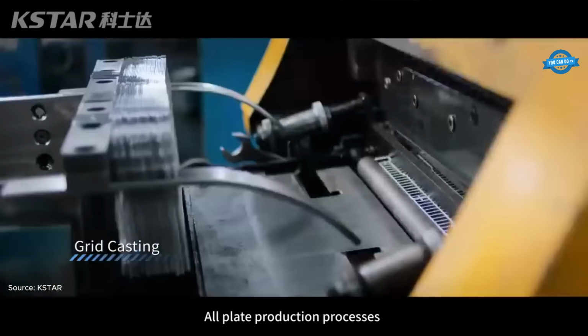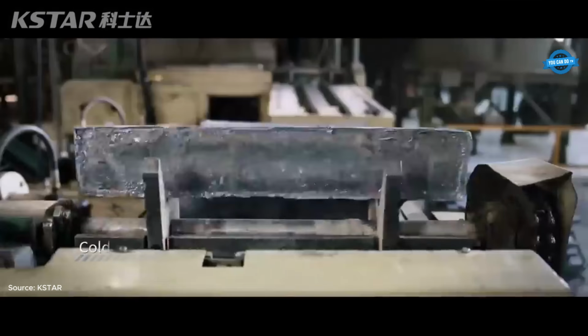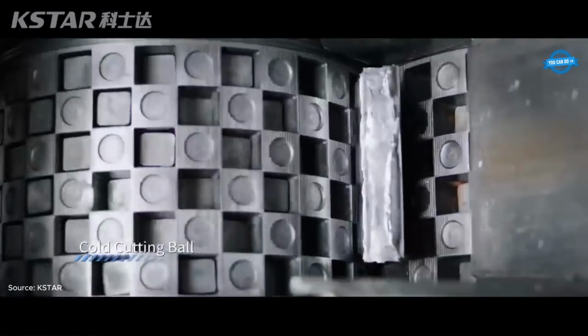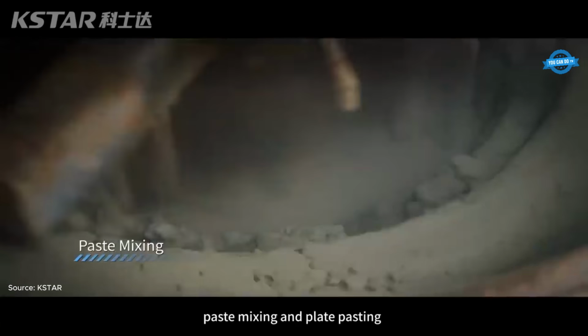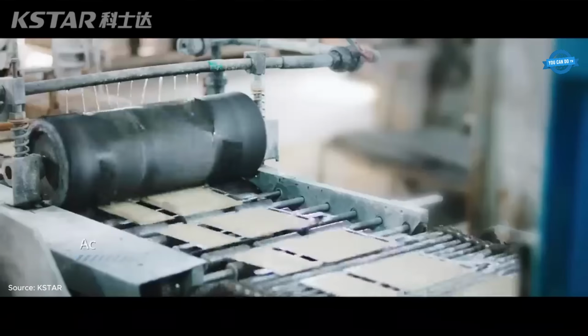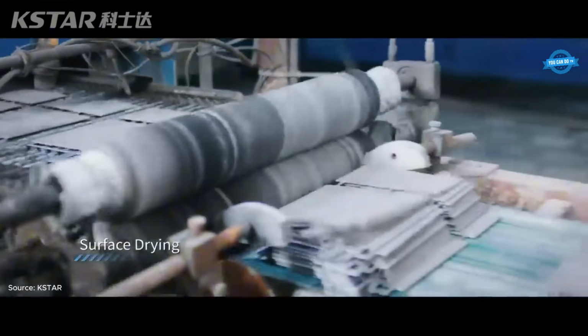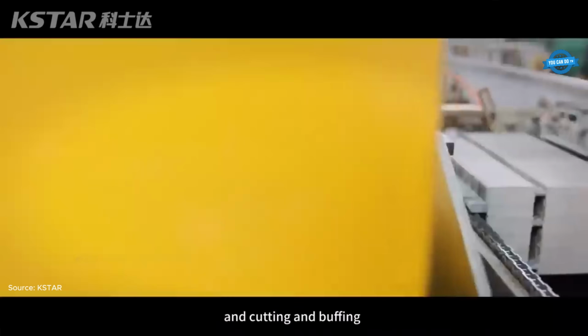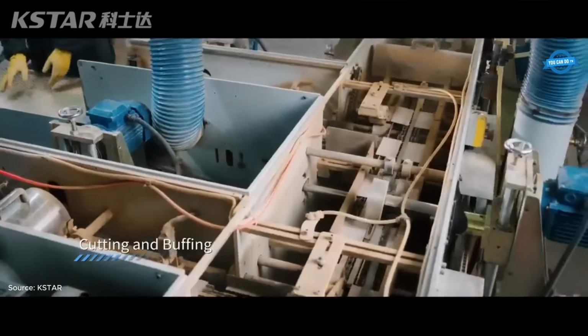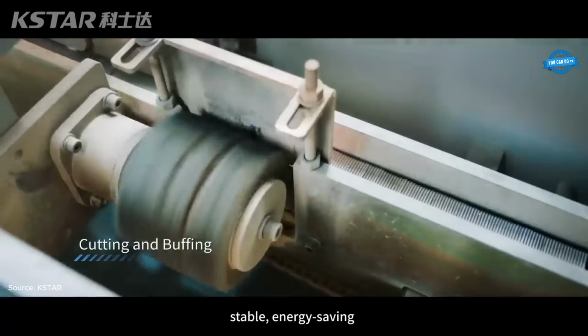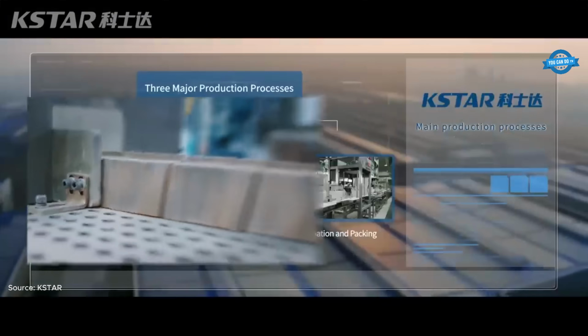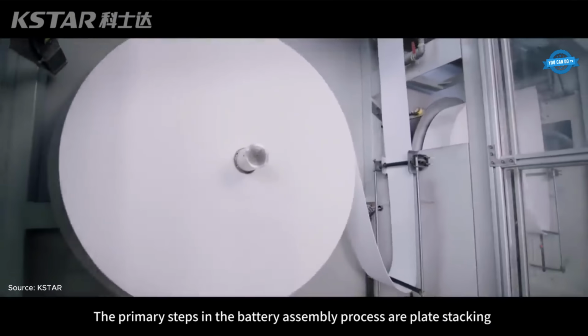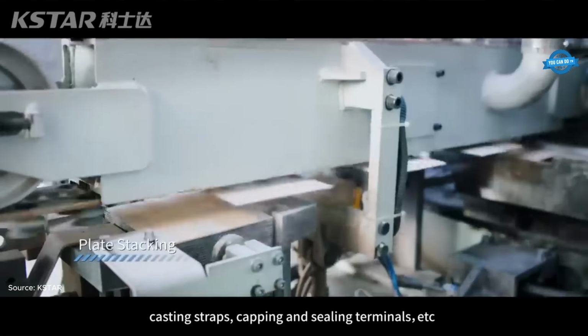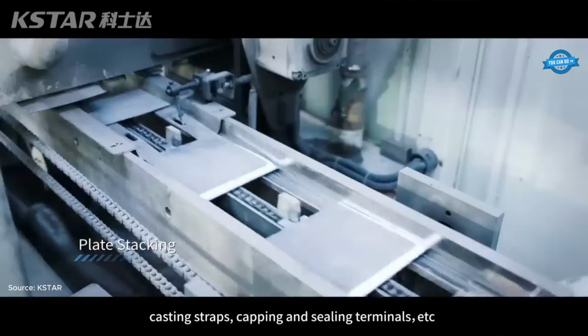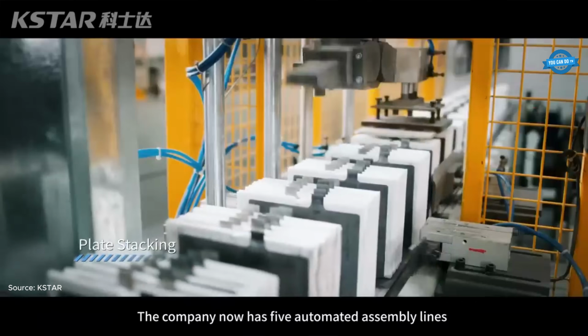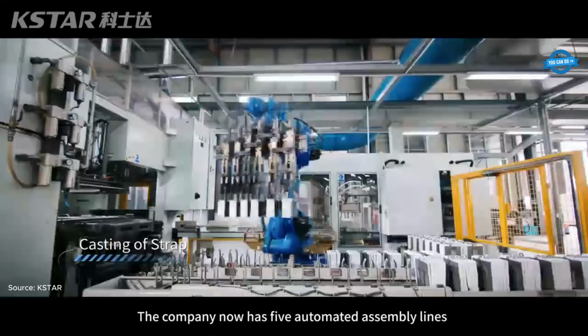Across global industries, K-Star batteries deliver dependable power, and that reliability begins deep inside their advanced lead-acid production line. The journey starts with plate manufacturing, the backbone of every VRLA battery. Raw lead is converted into high-purity oxide through controlled ball milling, blended with water, and mixed into an optimized paste. Automated pasting machines apply this material to precision-cut grids before the plates move through curing, drying, trimming, and buffing, each step monitored by sensors that safeguard consistency, energy efficiency, and environmental performance.